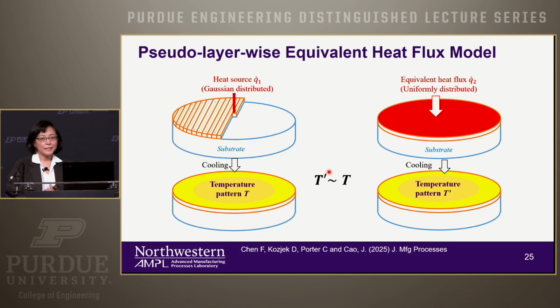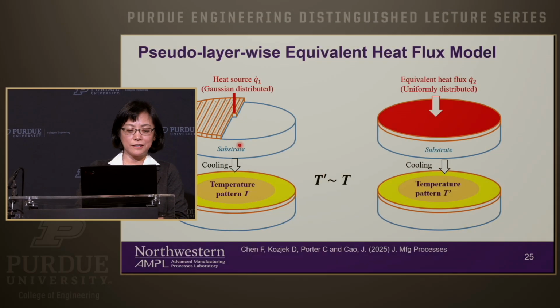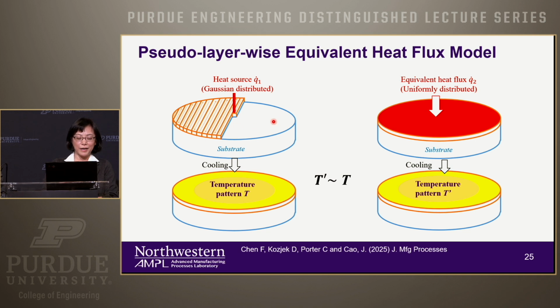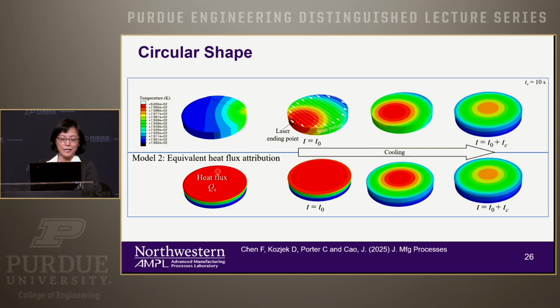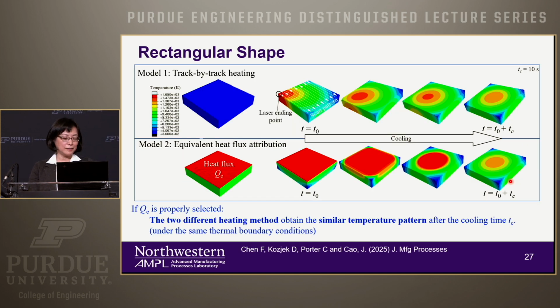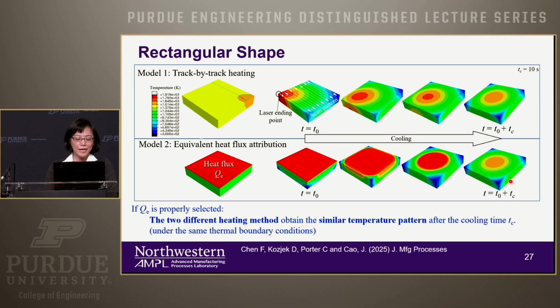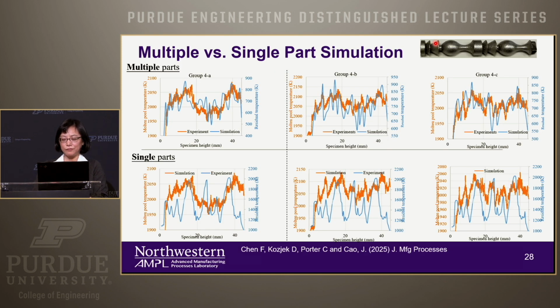The idea is pretty simple. We know the temperature obviously depends on the heat flux coming in. So instead of modeling the laser path, path-wise, can we create an equivalent heat flux model? Because after each layer you cool down, if you do this layer by layer scanning path-wise, versus just the equivalent heat flux, after a certain time they become equivalent. So we take this equivalent model, you can do square or circular cross-sections. It's almost like the unit cell model, right? Then we put those in, and we can simulate, for example, this one as we build up the entire plate. The first animation that you see is using this.